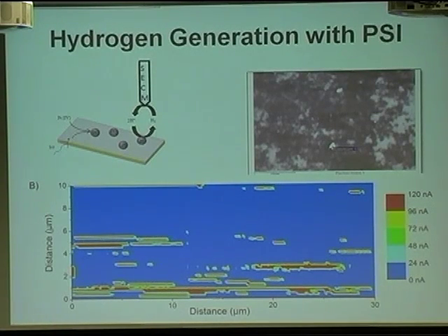And so this is our PS1 film, now with platinum deposit. The white areas you see here are platinum. Gabriel LeBlanc made these films, and Gong Ping in the audience here tested them. We're testing them with scanning electrochemical microscopy, where we take a tiny electrode and raster it over the surface. That electrode can do electrochemistry through solution back and forth with the platinum particles deposited on the surface. With that technique, we're able to detect where we have active Photosystem I connected to platinum on the surface.